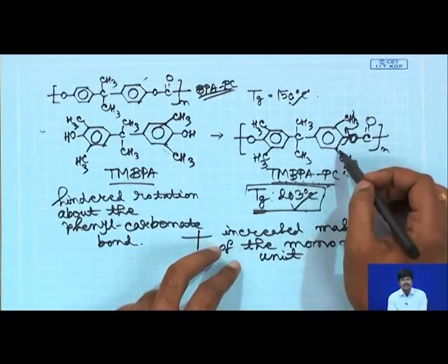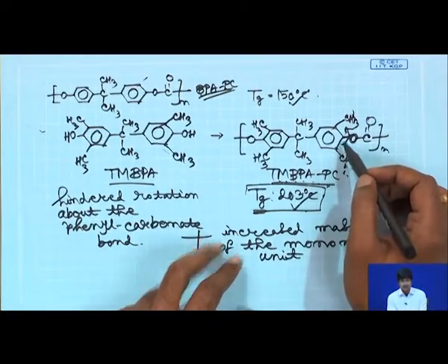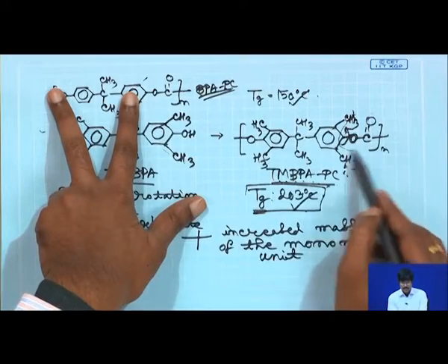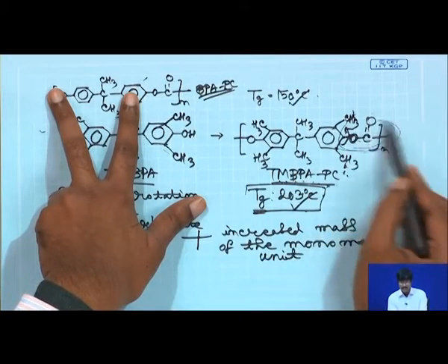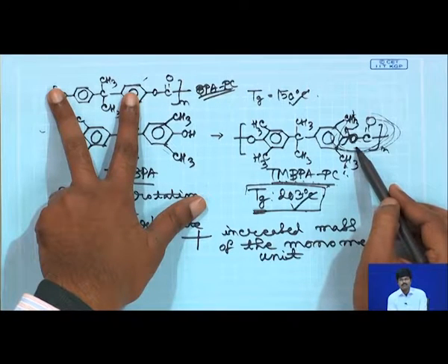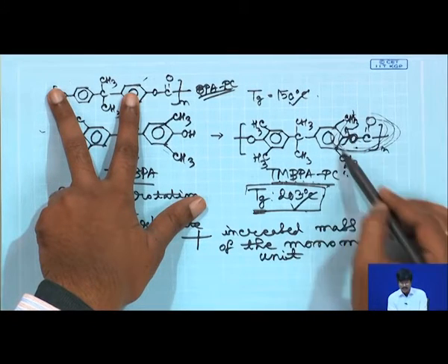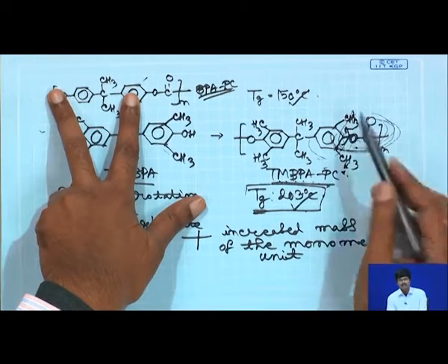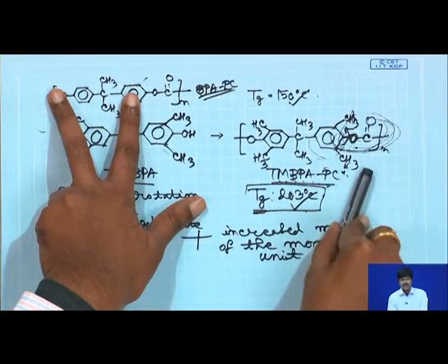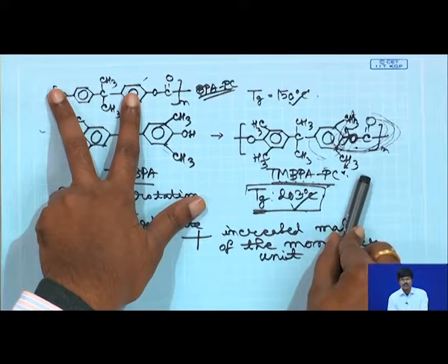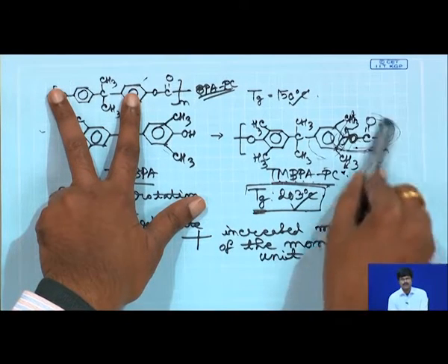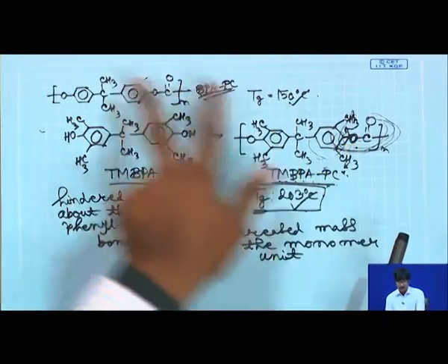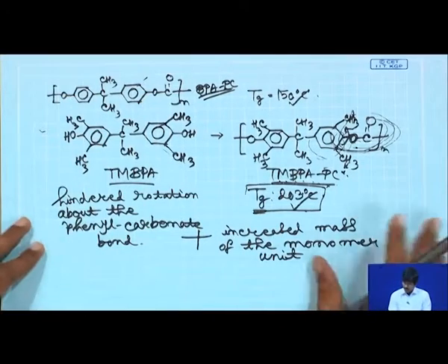and not only that, it will have a better hydrolytic stability if you compare with your bisphenol A, simply because you have actually decreased the accessibility of this ester to water further by adding these methyl groups. This was hydrophobic, no doubt. Now we have added the methyl groups. So, it is now also sterically hindered as far as the approach of a nucleophile is concerned to this ester. So, this becomes hydrolytically more stable with respect to your bisphenol A. All right.